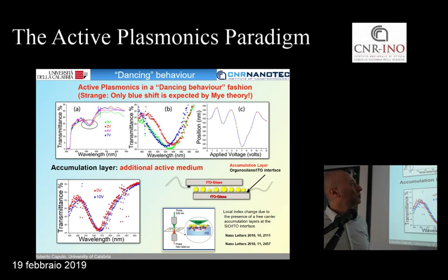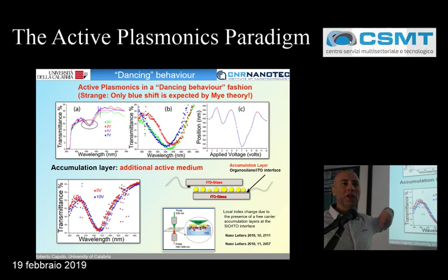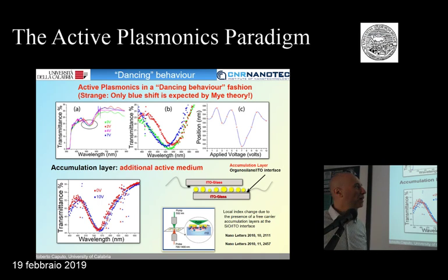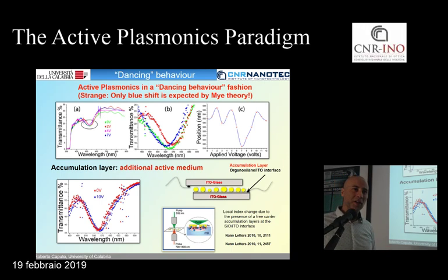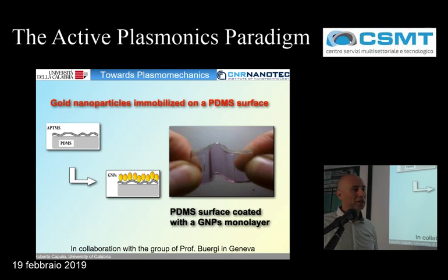So we obtain what we define as a kind of dancing behavior, because by increasing the electric field, we don't have a linear response of the resonance, but a change, a red shift and a blue shift, depending on the applied field. This was a result we didn't investigate in more detail, because we changed the mechanism of obtaining the plasmonics. In particular, we started moving to another possibility.